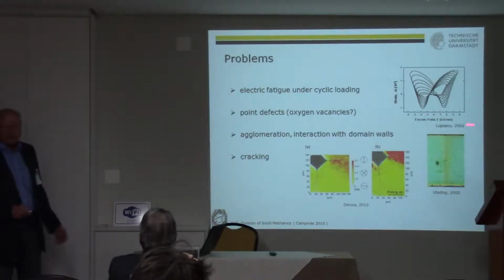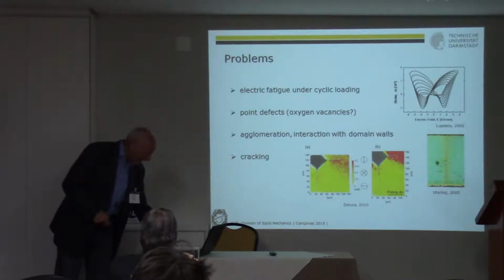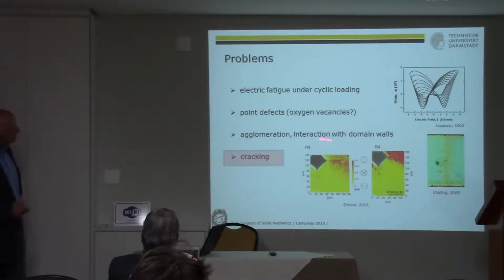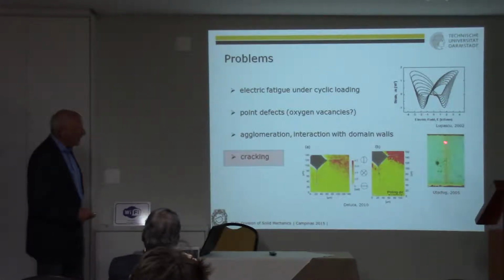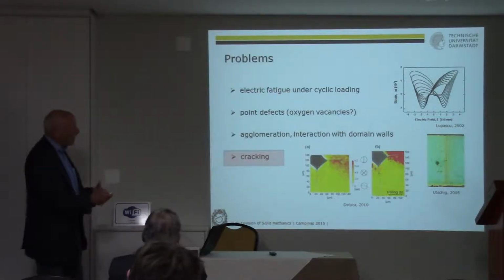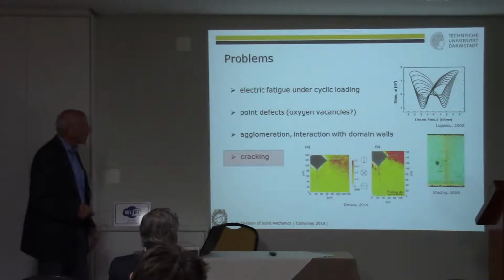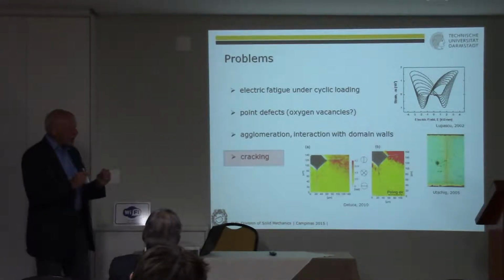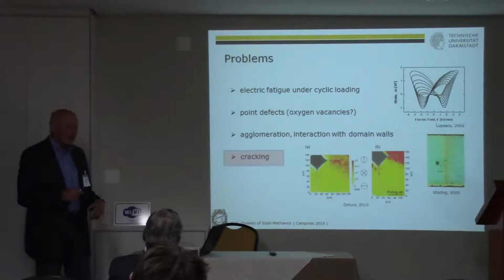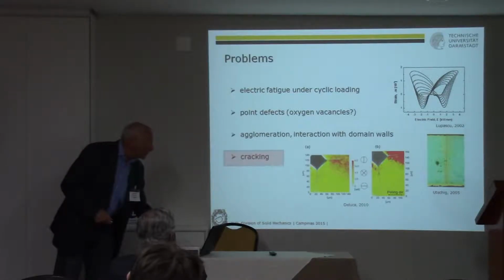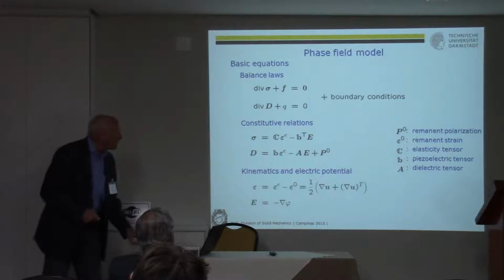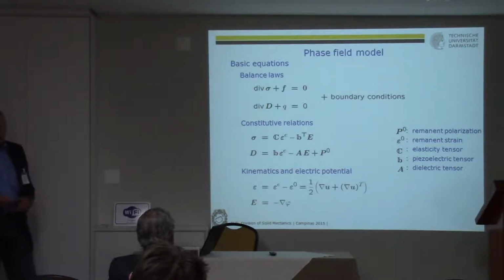Okay, as I mentioned just, but then there are other problems because it's a very stiff or brittle material. You have a problem with cracks, yeah. And so, because I came from fracture mechanics, I thought, cracking is one problem which might be interesting also for you here. Here you see from an experiment done in Darmstadt, a domain wall between, say, two domains with different polarization in a specific material, yeah, where the single crystal you had was really visible, yeah, with free eye, yeah, and where you very easily could see what happens, yeah.